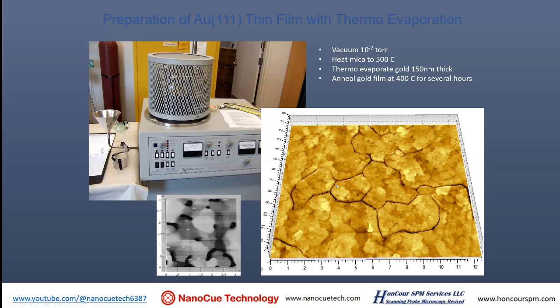Okay, so there's another problem with the sample. The second is that when you expose the gold surface to, say, ambient air, it attracts a lot of molecules from the air and becomes dirty. It becomes dirty very quickly. About an hour, it becomes dirty. You can see that the atomic step is visible at the beginning and gradually it's not visible. That's not because the atomic step disappeared. That's because the surface gradually attaches a layer of contamination.